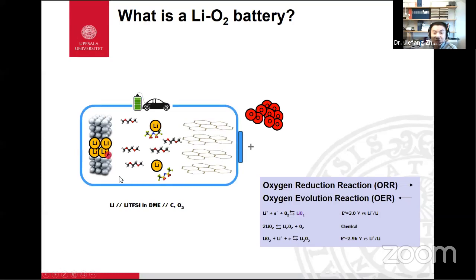So during discharge, the lithium will react with oxygen to form lithium superoxide, and then the superoxide will again react with lithium and electron to form lithium peroxide. So this is a two-step process. But in the decomposition, this is a one-step process. It will decompose to lithium and emit oxygen also. So we should keep in mind that the ideal electrochemical reaction is the lithium peroxide formation and decomposition.